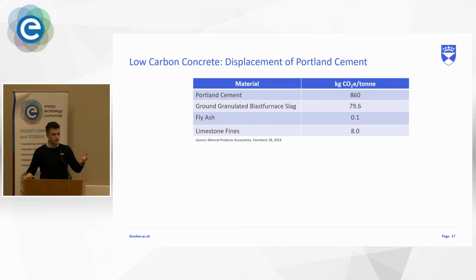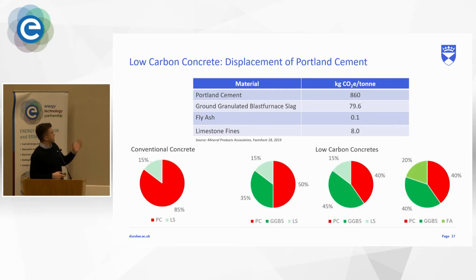Okay, but what do we consider to be a low-carbon concrete? A conventional concrete would look something like this. So we've got 85% of Portland cement with a little bit of addition of 15% of limestone. So technically, anything below 85% could be argued to be a low-carbon concrete. Now, in this project, we tried to go as reasonably low carbon as we potentially could, without compromising the performance and durability. And so we ended up pushing the PC replacement up to 50 or even 60% PC replacement with GGBS, limestone, and or fly ash.